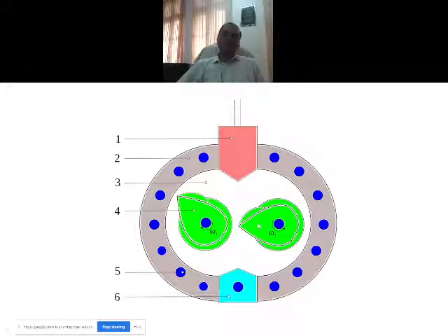So where does shear happen in the whole process? Look at that, this gap is small and this gap is less. By the time it is in the horizontal, actually in the 9 o'clock position here, the gap is minimum possible. So imagine it is sweeping from here and going up like here. So that means the material will here experience a shear deformation. This will be folded and then sheared and then again folded. So shearing is happening at this point between the rotor tip and the mixer wall. Between the rotor tip and the mixer wall, there is mixing happening.